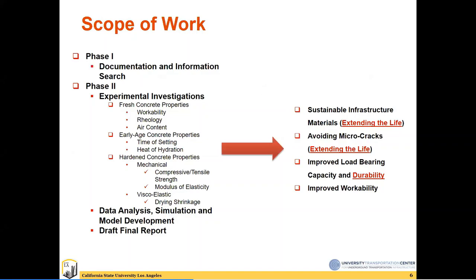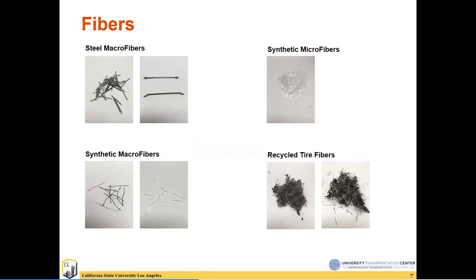So right now we are in phase two of this project, and we are testing a series of fresh concrete properties, as well as evaluating some early age properties and of course hardened properties that could include compressive or tensile strength, modulus of elasticity, and also investigating the drying and plastic shrinkage. The goal is to see the impact of sustainable, non-cementitious materials such as fly ash or slag, and for the most part investigating the impact of recycled fibers on the performance, or how they can enhance the performance of the SCC. These are some of the fiber types that we are using in this project. There are some more coming in.